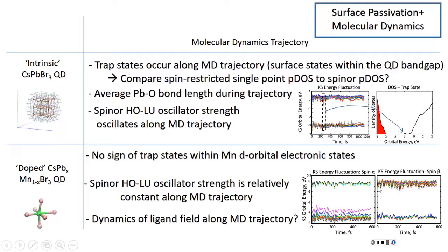And then spin beta, that's where all the valence or unoccupied d states are, where the transitions would come from. They're like the first five. They're not very spaced out from the perovskite conduction bands, but you can kind of resolve them if you look close enough. And you don't see any trap states that poke through those either. So along the trajectory, they're unaffected by trap states. And if you looked at the oscillator strength from the spinor orbitals during the trajectory, they're basically constant but very low, which follows our expectation from the beginning of the dopant being unaffected, or the oscillator strength being unaffected by trap states.